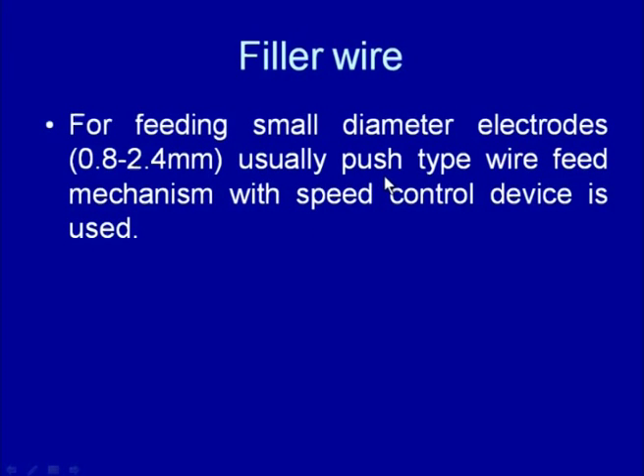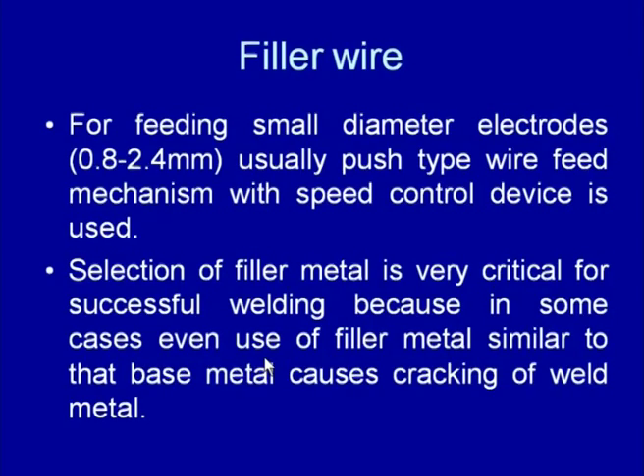The push type is preferred because it helps to feed the wire in the arc zone without the tendency to break it. Under the pull type wire feed systems, the wire will have a tendency to break. So, to avoid that breaking tendency of the filler wire, the push type of wire feed mechanism is preferred. However, the selection of the filler material is crucial in the sense that sometimes the selection of the same filler material as that of the base metal composition leads to cracking of the weld metal. So, sometimes the filler material is intentionally selected of a different composition, so that the thermal expansion coefficient and the solidification temperature range are such that it does not cause much cracking of the weld zone.